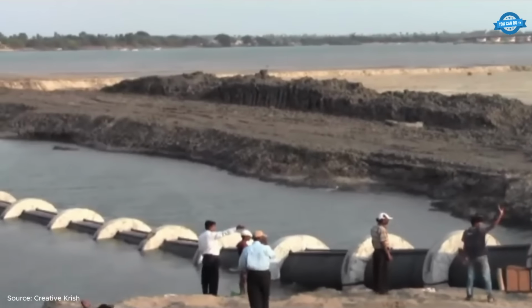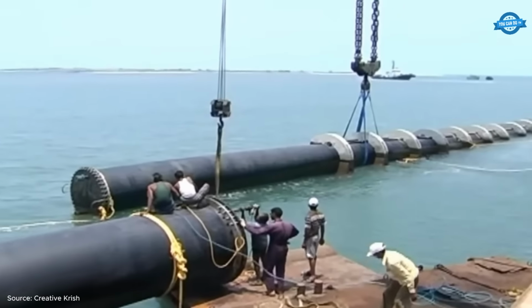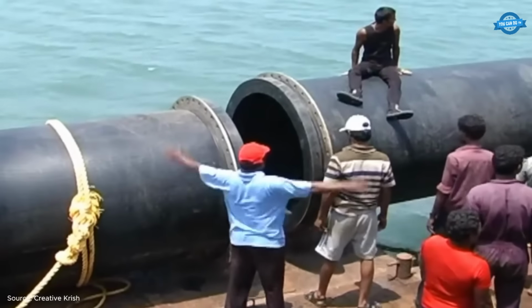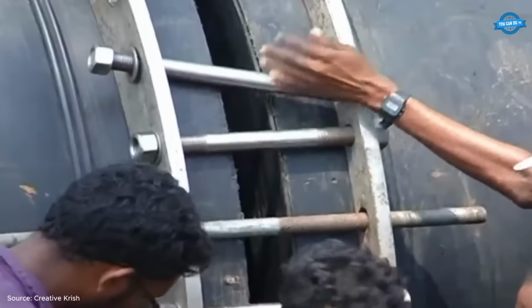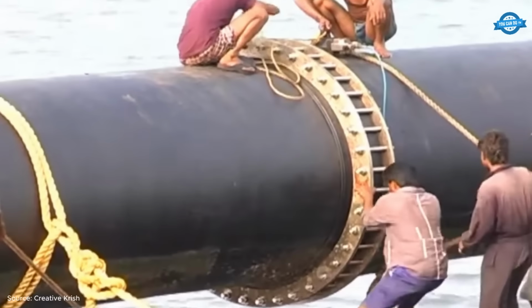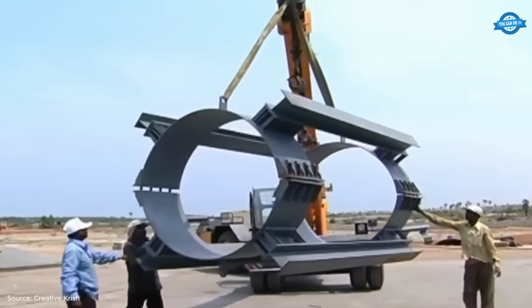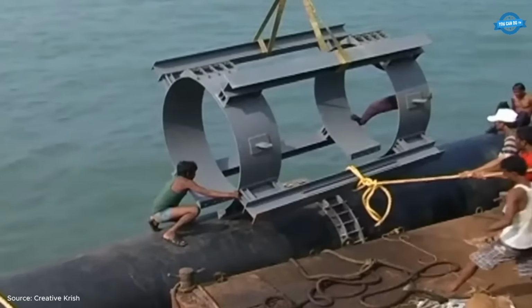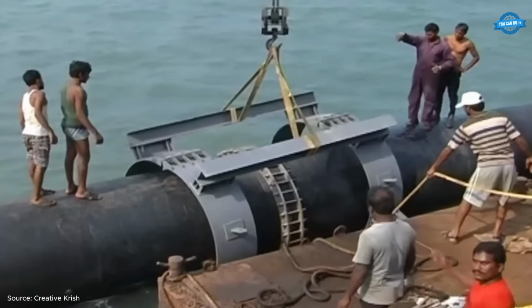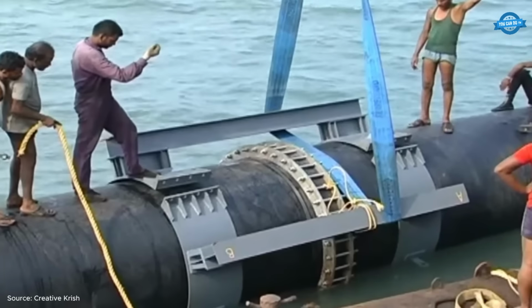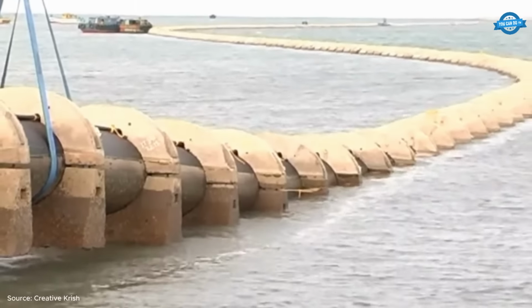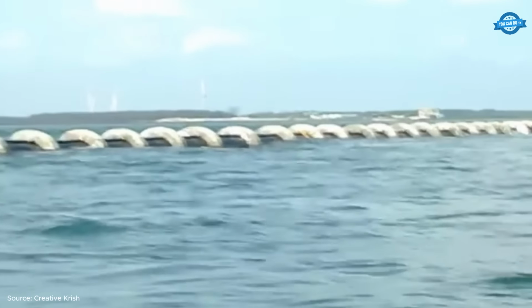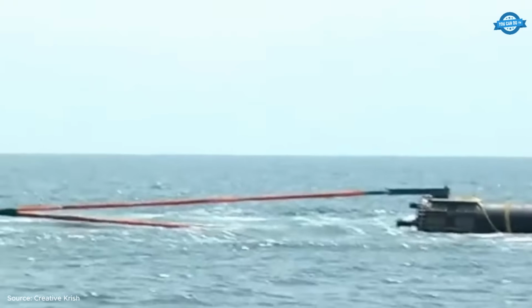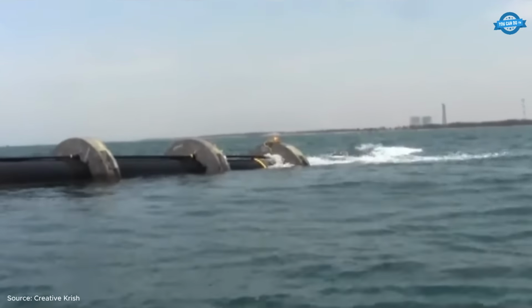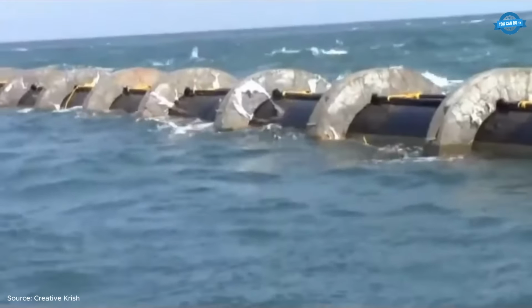Production and preparation began with pressure testing of large polyethylene pipes to verify structural integrity and leak resistance. Reinforced concrete anchor blocks were then installed along the route to stabilize the pipeline against underwater currents and buoyancy forces. After assembly, the long pipeline sections were carefully towed offshore to the installation location. Engineers installed flange joints and bend restrictors to maintain alignment and protect the pipeline from excessive stress during operation.